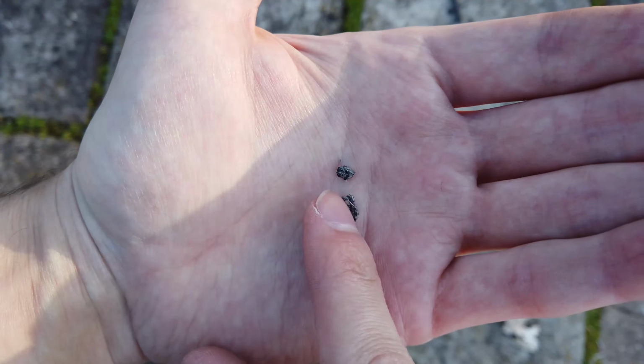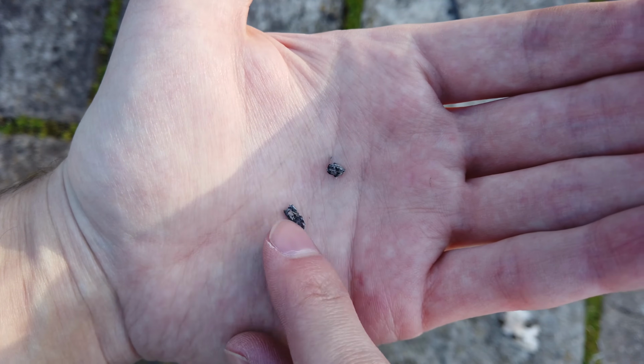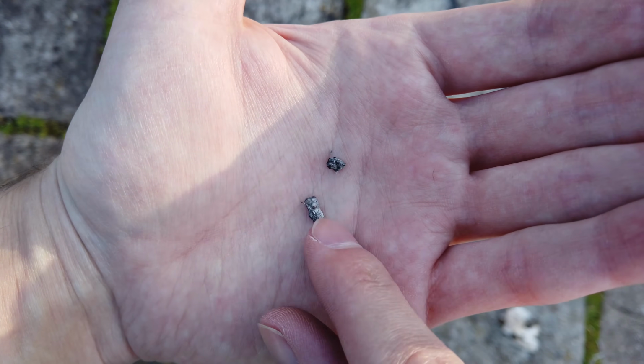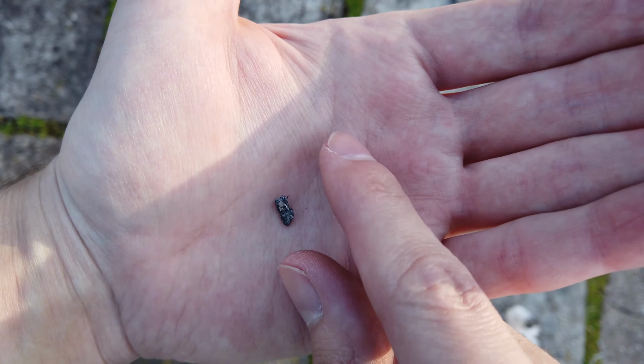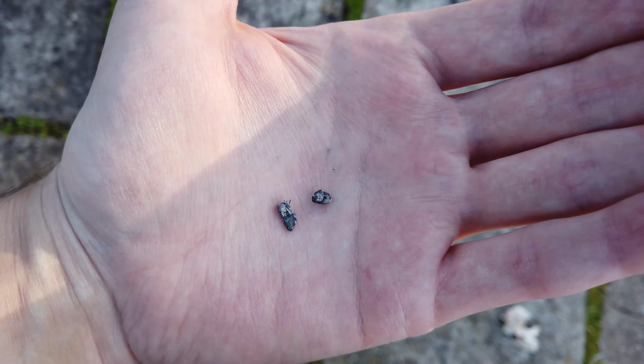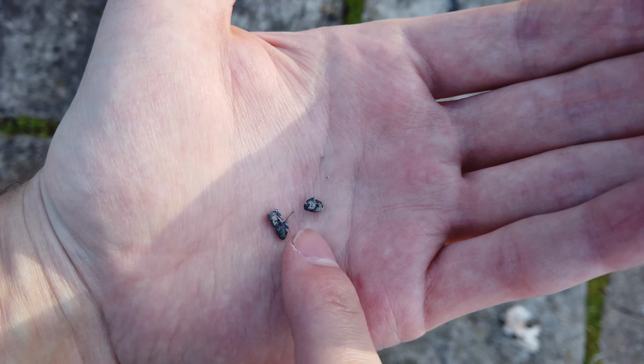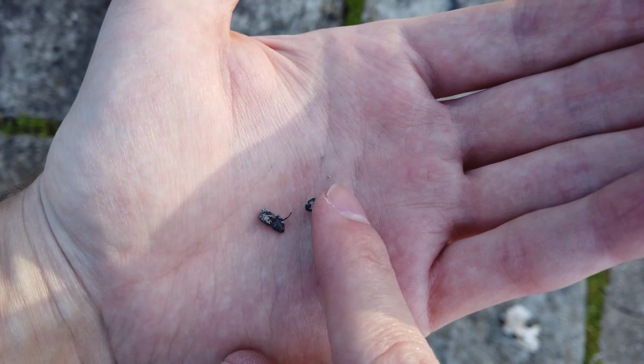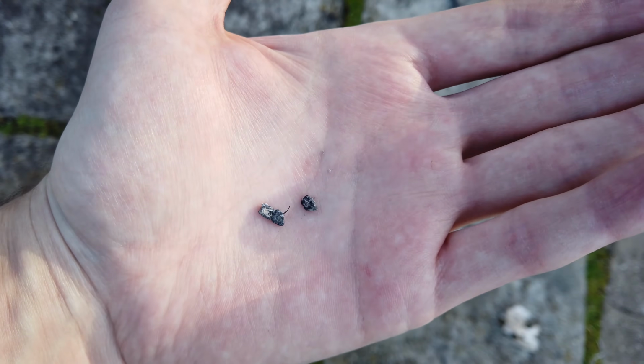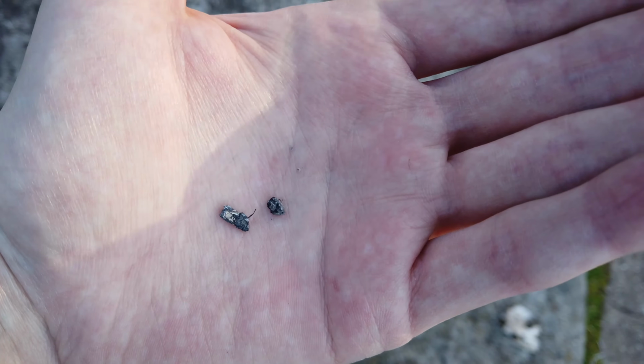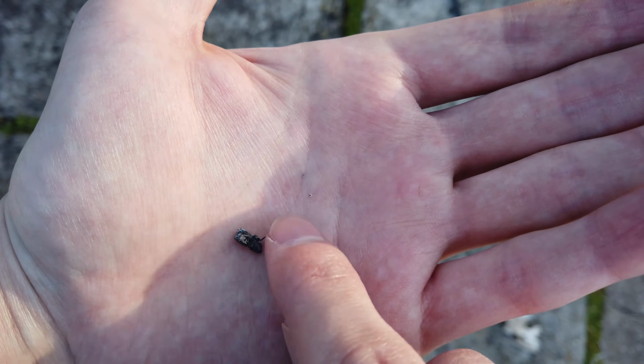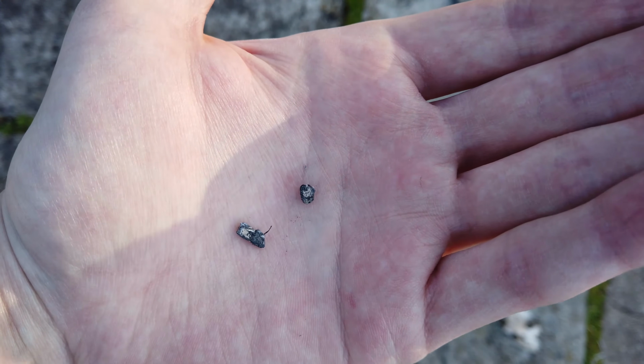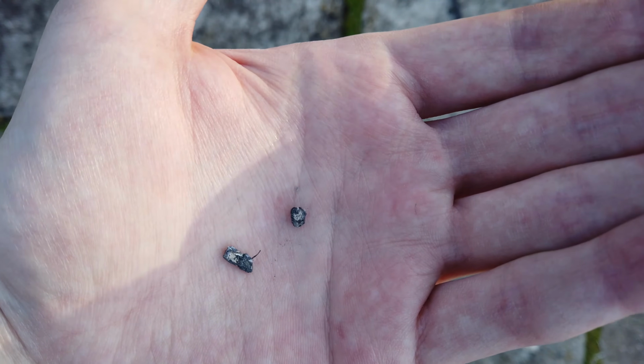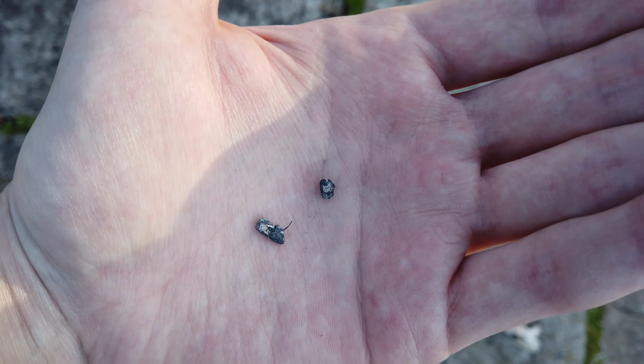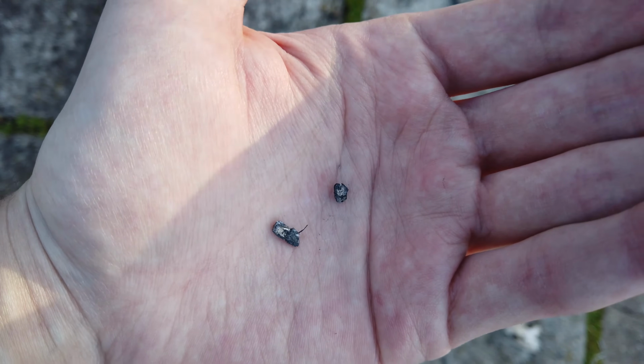There we are. I was able to remove a small amount of it from the scooper that I was using. This is about half of what we were able to extract in that first 15 minutes. I'm very sure this is calcium because it is, as you can see, rather shiny in places. So to actually test it properly, I'm going to chuck half of this, just this small one here, in some water, and if it starts generating hydrogen, we know that we have actually made calcium here.